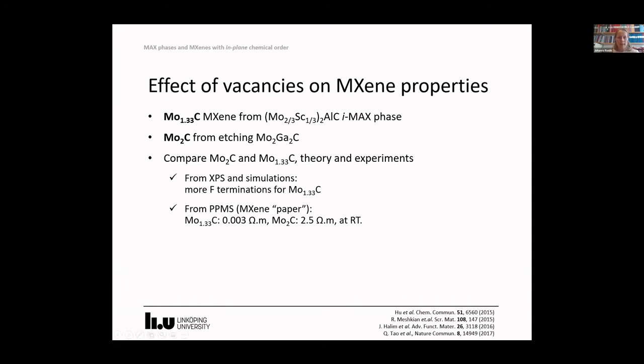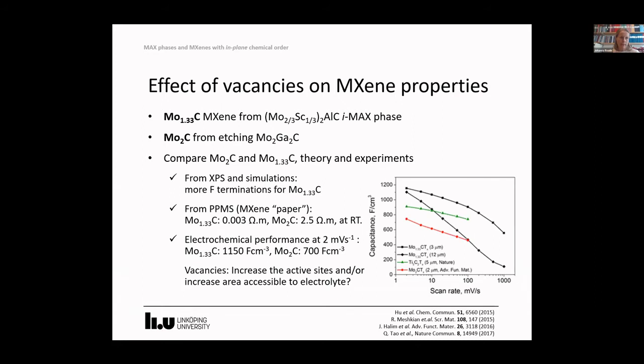Resistivity measurements in linear four-point probe geometry on 10 micron films show a difference of three orders of magnitude in the resistivity of these two MXenes. Also, electrochemical performance in 1 molar H2SO4 shows similar behavior as other MXenes, but at 2 millivolt per second, we have for the vacancy MXene around 1150 farad per centimeter cubed, and for the Mo2C, a bit more than 700. The higher conductivity of the vacancy MXene is most likely a part of this result, but whether the vacancies increase the active sites and increase the fraction of the electrode accessible to the electrolyte needs to be further investigated.